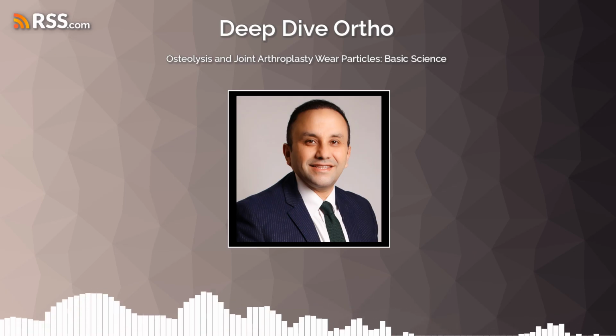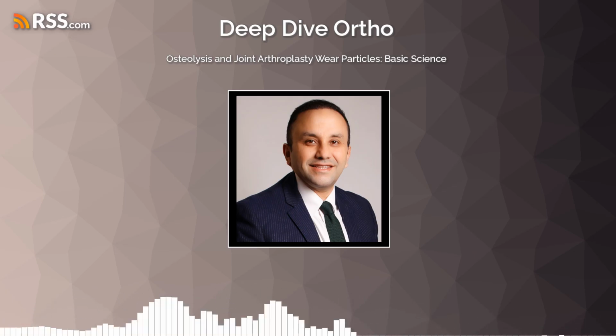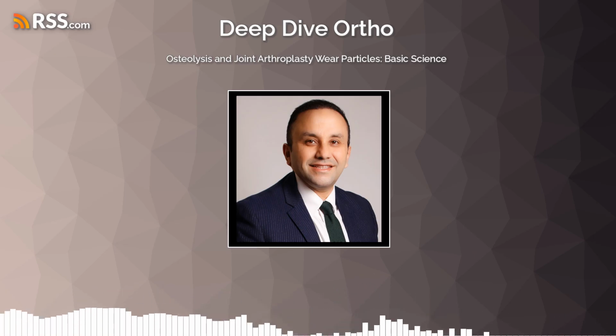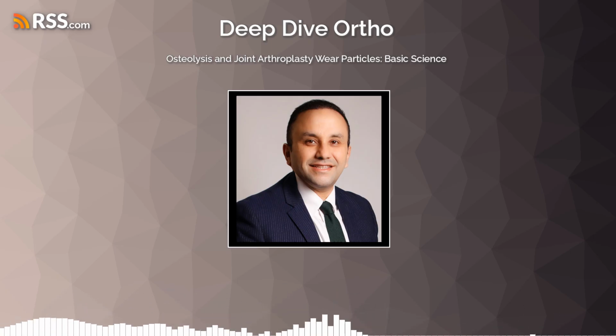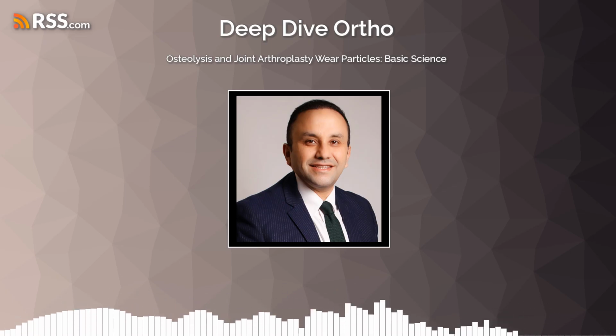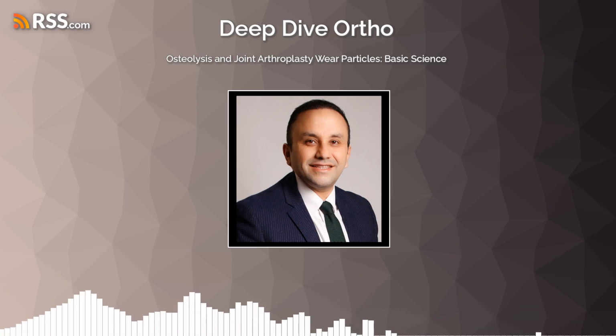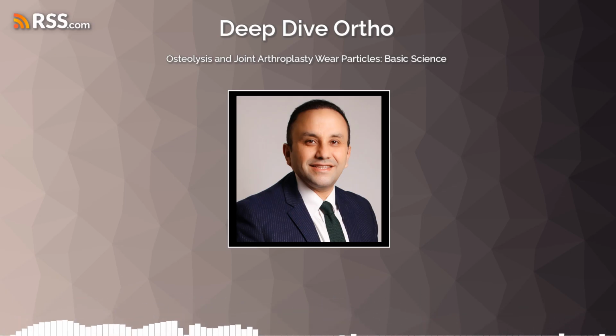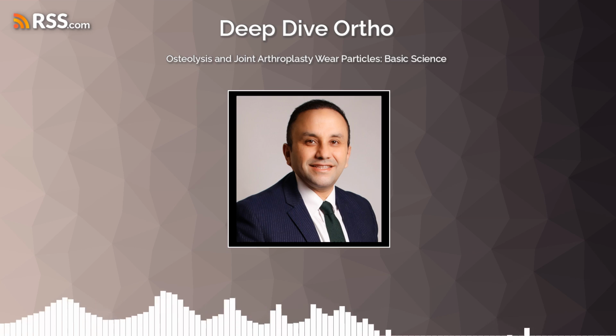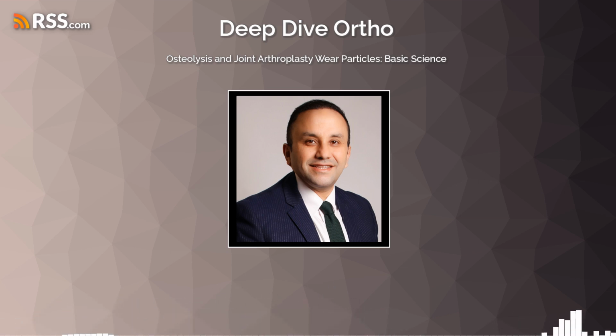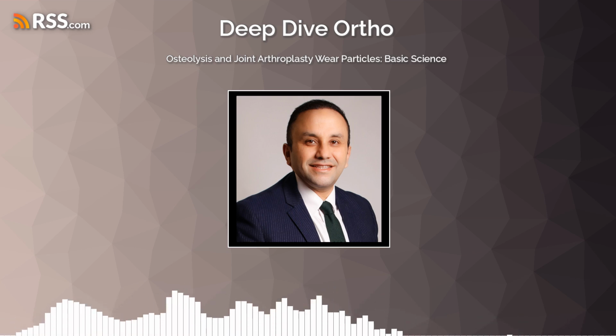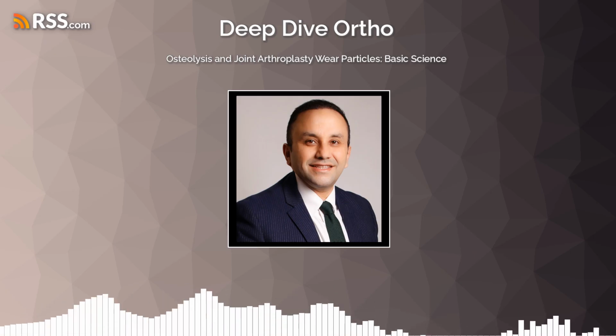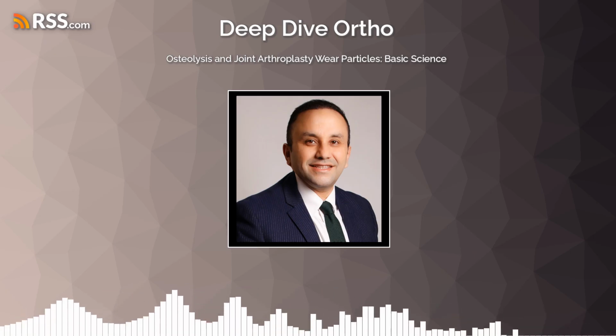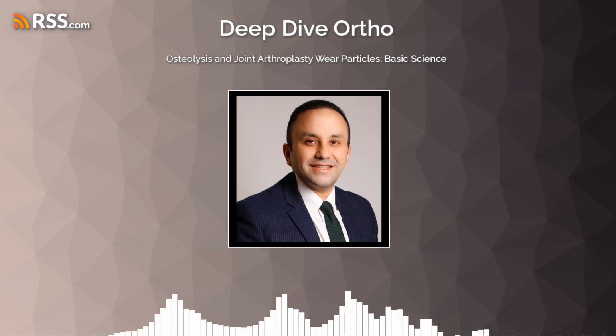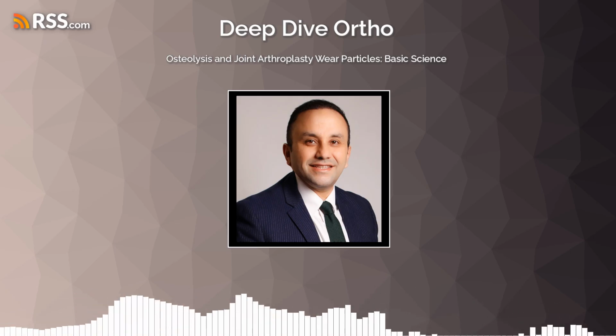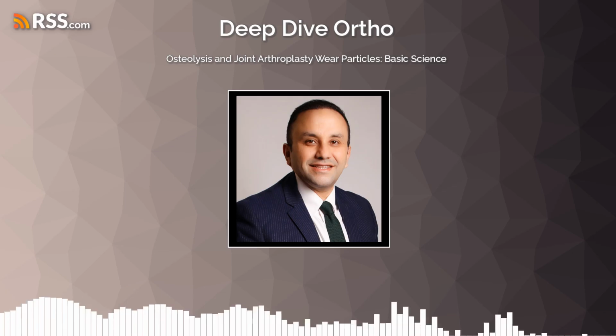And the third pattern. And finally, we have stress shielding. Now, while this is still a form of bone loss, it's slightly different in its pathogenesis. It's primarily a consequence of biomechanical factors rather than direct particle-induced inflammation. How so? Stress shielding occurs when the stiff implant component bears too much of the physiological load that the bone would normally experience. According to Wolff's law, bone remodels in response to mechanical stress. It adapts to the loads placed upon it. Exactly. It strengthens where it's loaded and atrophies where it's not.